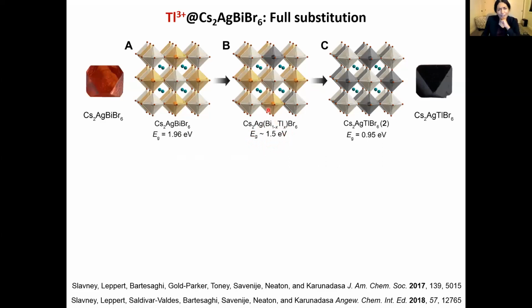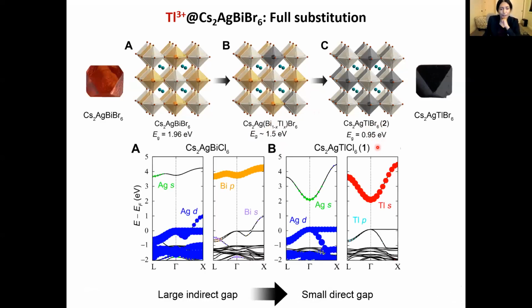And just out of curiosity, we decided to go all the way to the all thallium material, and the band gap now goes down to the lowest value ever seen for a halide double perovskite. So moving from silver bismuth to silver thallium, 2 very good things happened. The large band gap went to a small band gap, and the indirect gap moved to a direct gap. And we can understand exactly why this happens.